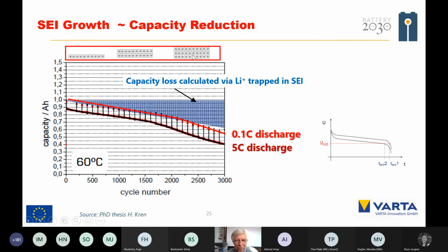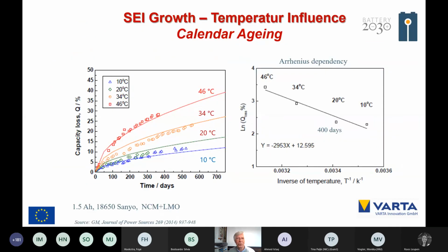For 5C discharge, we have deviations, that's clear, because with the higher current, we have a lower discharge voltage, and therefore the capacity is also reduced. So, and then you have temperature influence on the growing of the SEI. You could measure that without any cycling. You put only the graphite electrode, the formatted graphite electrode, in a thermostat, and then you measure the capacity loss, 10, 20, and so on.